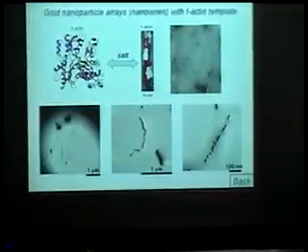We decided to focus on a very common protein called actin, which is a very important cytoskeletal protein. This is a monomer called G-actin. In the presence of physiological salt, it binds with ATP and self-assembles into these extensive fibers shown here. We have developed ways to use this process, and this process is very reversible. If you take away the salt, it goes back to the monomer.